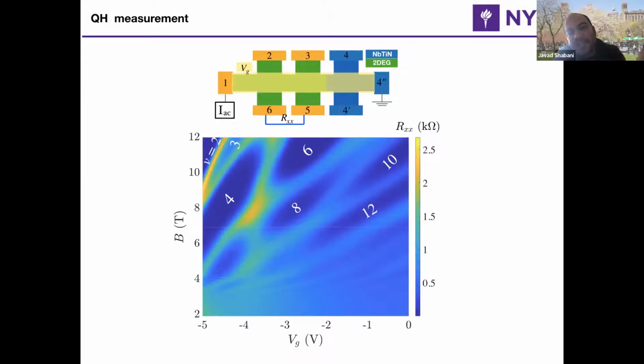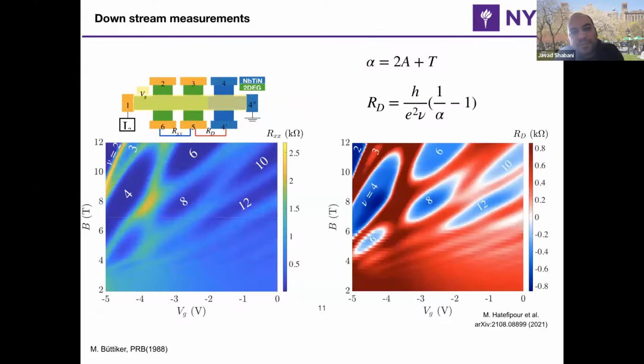And if you basically get an RXY equivalent of this, we can actually mark the filling factors. So that's how we are basically saying 8, 12, 6, 10, right? And then we measured the interface, which we were very surprised by, right? So if you measure on that schematic on the top left, basically now measure across the interface, for example, it was supposed to be 4 on the left graph. Now on the right graph, still we have 4. The shape is quite similar.